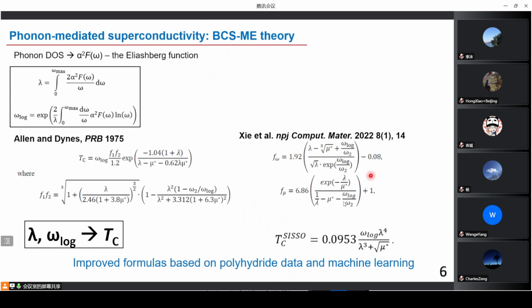So they modified the Allen-Dynes formula, modified the coefficients to get better agreement with experimental results in polyhydrides, and they also developed a simplified formula using, again, machine learning. So I will use both of these models, actually three models, in my presentation to show how to get maybe estimates for the maximum Tc achievable in hydrides. So if we know the EPC coefficient, the electron-phonon coupling coefficient lambda, and if we know the logarithmic frequency, we can get Tc, the critical temperature of superconductivity.